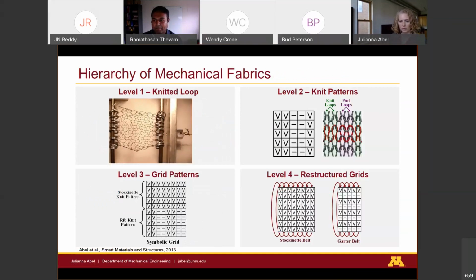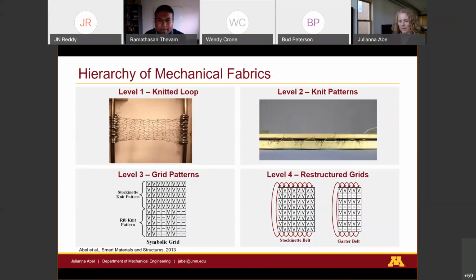So we can have knit and purl loops in certain patterns. This happens to be a rib pattern of varied columns. It's the edge of all your sweaters. And when you heat it up, it goes from a flat surface into this corrugated wavy surface. So you can imagine using this for some type of flow control over a surface.